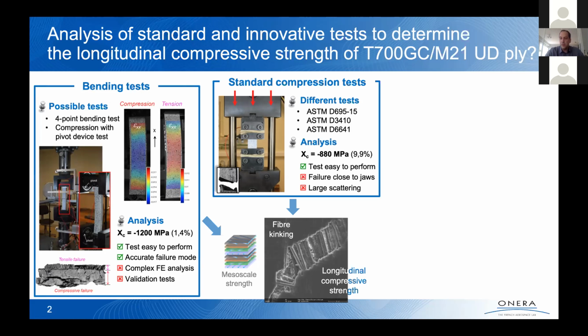The point is that most of the time you are going to obtain premature failure under the loading span. This is the reason why at ONERA we have proposed a compression with pivot device test. So such an experimental device allows to generate bending loading by offsetting the midplane of the laminate with respect to the rotation axis of the pivots. If the offset through the thickness is equal to half of the total thickness of the laminate, you are going to generate a quasi-pure bending loading.